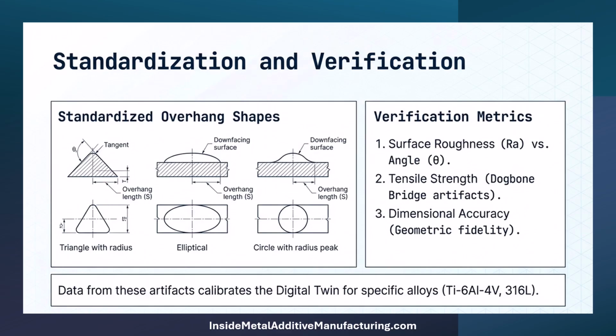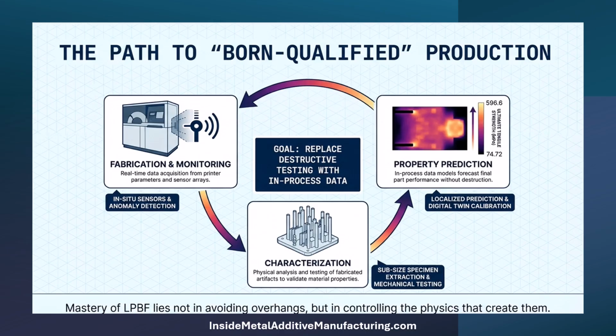We use standardized overhang shapes, triangles, ellipses, and circles to calibrate our digital twins. We verify success by measuring surface roughness against the overhang angle and testing tensile strength using dog bone bridge artifacts. In conclusion, the mastery of LPBF isn't about avoiding overhangs. It's about controlling the physics that create them. By closing the loop between fabrication, characterization, and property prediction, we can finally replace destructive testing with reliable in-process data.